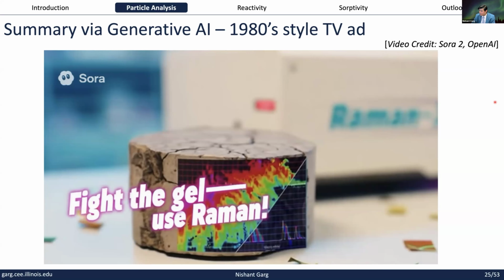Second question is XRD versus Raman from Tariq. Which technique is best for analyzing crystalline phases, and which is best for amorphous phase? Yeah, I would say X-ray diffraction is the gold standard, and it's a very well-established technique for analyzing crystalline phases. So this is why we use XRD as a North Star to do our initial calibration and to really see what parameters can be good for Raman to catch some of those crystalline phases. That being said, once this initial work is done for certain systems, then Raman can also be quite helpful and very complementary in analyzing these crystalline phases.